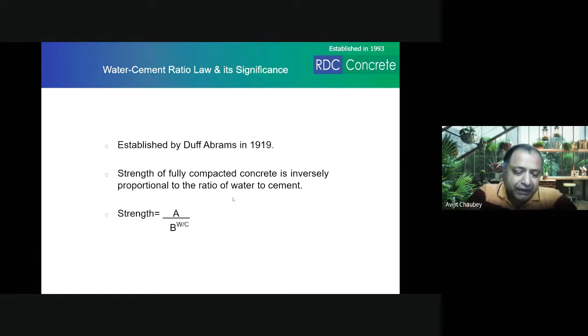And every time I end up getting that the highest significant factor for strength is the water cement ratio. Of course, in the year 1919, the only thing that they were using was cement. They never used fly ash or slag as replacement. So Duff Abrams did not test percentage fly ash, percentage slag, or percentage ultrafine kind of a material with this.